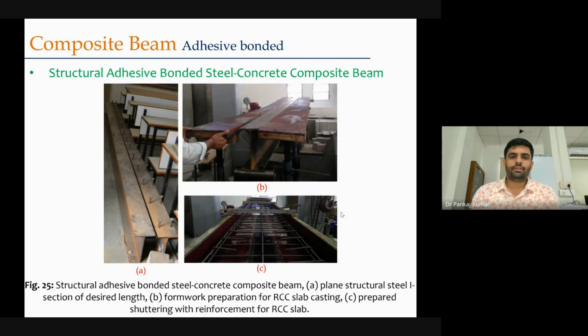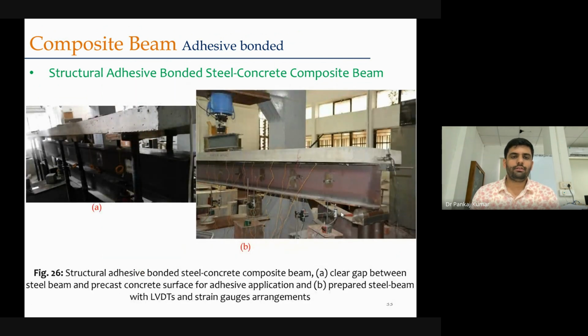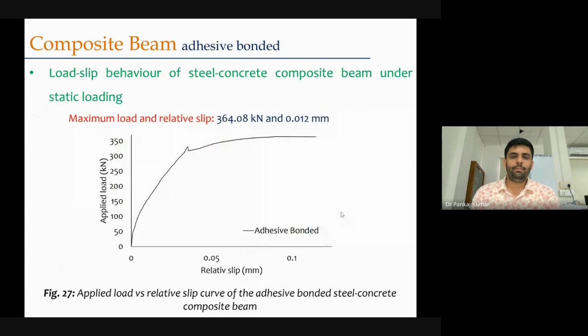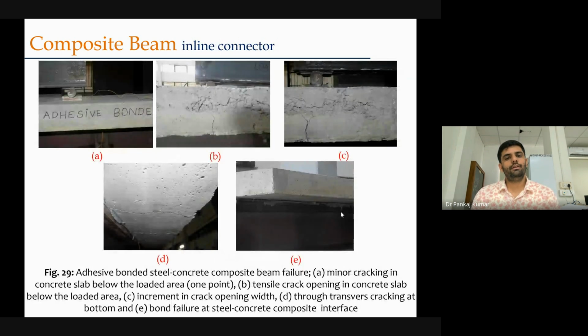Then for the third case, we took a simple beam. Over that we cast the concrete slab, put adhesive in between, and then tested it. This is the typical arrangement for the adhesive bonding. For that also, we measured the ultimate load capacity as well as the engendered slip at the interface level. So what we concluded from there: